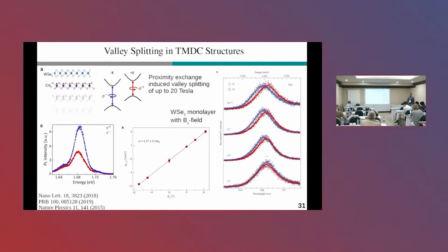So if you consider a tungsten diselenide on top of chromium triiodide, which is also a ferromagnetic semiconductor, then due to proximity-induced exchange coupling, a valley splitting corresponding to around 20 Tesla will intrinsically arise. So these are the data. And this additional quenching of one photoluminescence peak for the sigma plus comes from the band structure simply. But still, these two peaks are split. That would correspond to around 20 Tesla of external magnetic field.